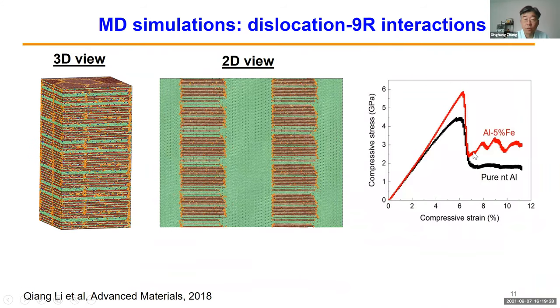Another question we need to address: we've measured experimentally that this aluminum alloy is pretty strong, but how do we explain this? So we turned to our colleague, Jian Wang, at the University of Nebraska, Lincoln. We asked him, can you simulate this phenomenon? The first experiment he did was to introduce stacking faults in aluminum. It turns out to be unsuccessful, because if you introduce stacking faults, highlighted here